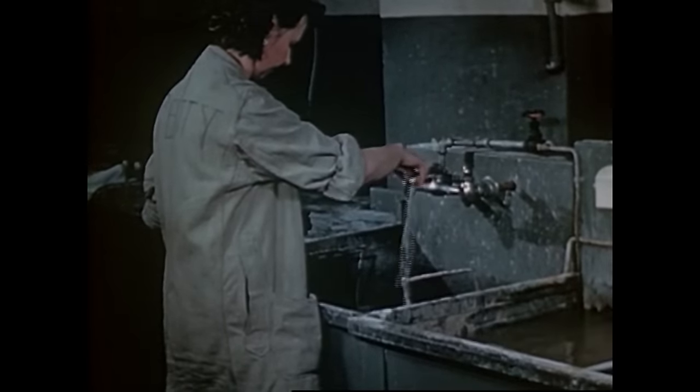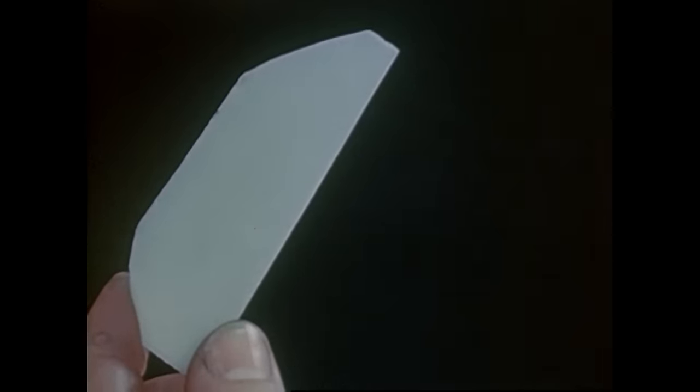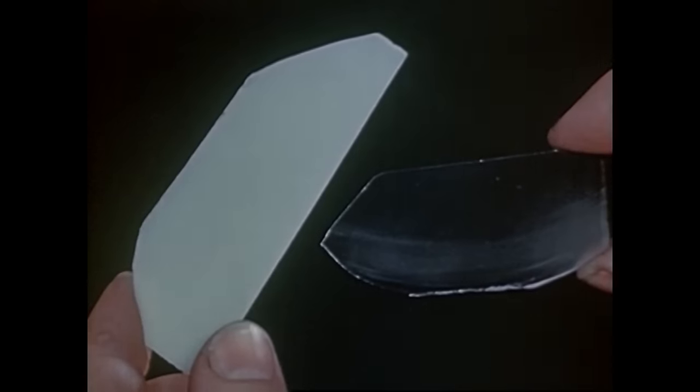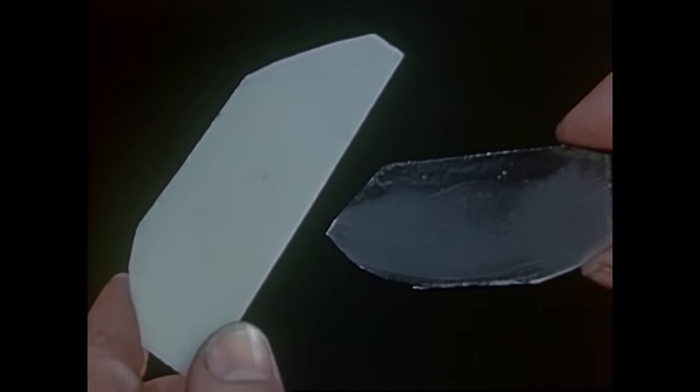The etched wafer has a white surface. The difference between an etched and an unetched wafer is readily seen. In looking for twinning on etched surfaces, the inspector sits before a small turntable and rotates the wafers under a concentrated spotlight. Differences in sheen of the surface bring to light any twinned regions.